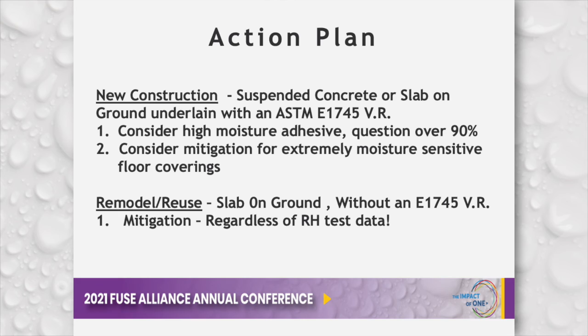So if we're going to have an action plan, I'm saying that with new construction, whether it's suspended concrete or slab on ground, underlain with that high quality vapor retarder, we can consider a high moisture adhesive. But I would have you question anything over 90%. And the reason for that question is that at 95% relative humidity, it takes a 2-degree Fahrenheit temperature shift to cross dew point. And if we cross dew point, we're going to turn relative humidity into liquid water. And once it's liquid water, guess what happened to all the warranties that were offered to you? They're gone because it's no longer relative humidity.